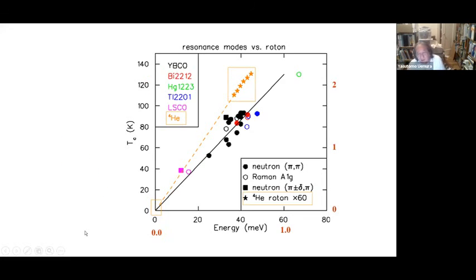So we can extend this analogy and see that, in the case of cuprates, the resonance mode is a good candidate for the role of rotons. In fact, if you plot the resonance mode energy versus TC with the same aspect ratio, you have this, and the ratio is about the same as the ratio for these rotons.